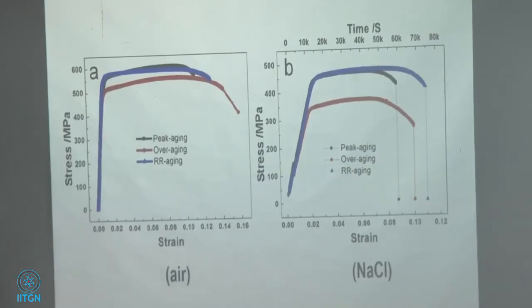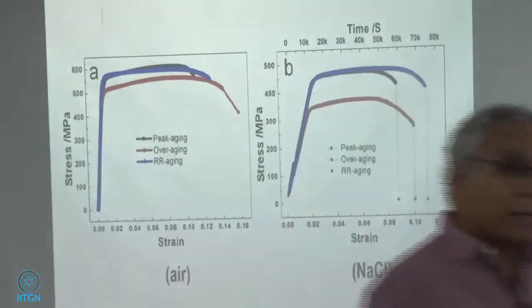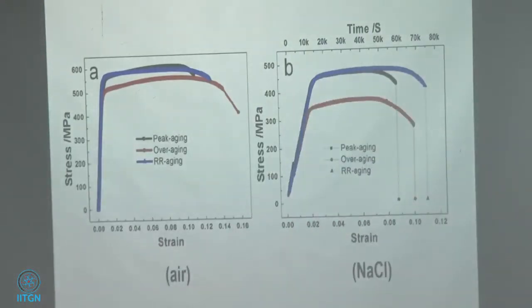Beautiful. So your experiment is good, right? You have produced, by using retrogression reaging, at least on the lab coupons, a strength as good as T6 and as good as T7 when it comes to corrosion. Just by using a double age treatment where you left the matrix precipitates as they are so you can get the strength, okay? And you refine the grain boundary precipitates by the retrogression reaging.